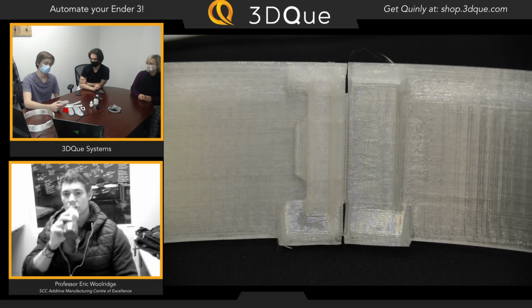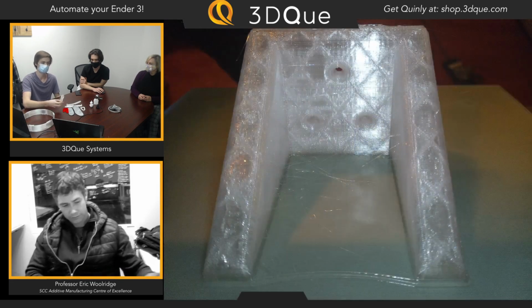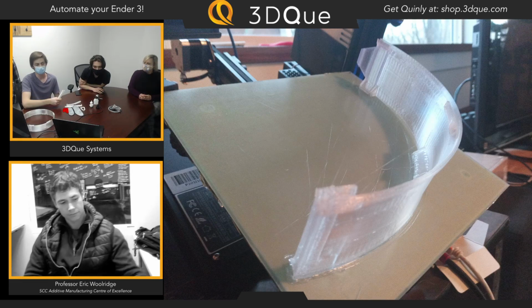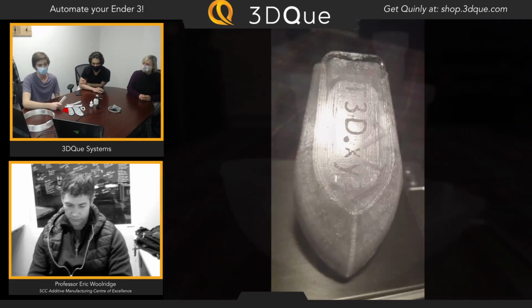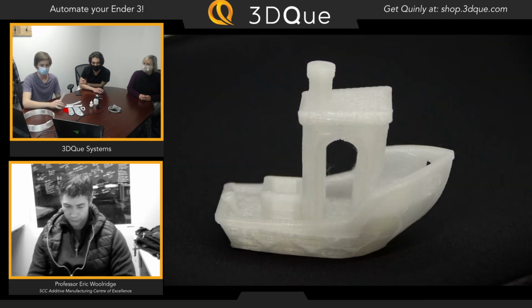So, we know that our build plates work best when we print these materials on a hot bed, and the bed has to be hot enough. So for the Ender 3, what we had to do is figure out how to get the bed hotter than 110 degrees so we could print polycarbonate. So there's a very simple upgrade that I did. It cost about $20 total for a couple rolls of tape and some foam. And it was essentially just a layer of insulation underneath the heat bed. And it was super simple. It took me about half an hour to do. I took the bed off, applied some tape, applied some foil tape over top of that.